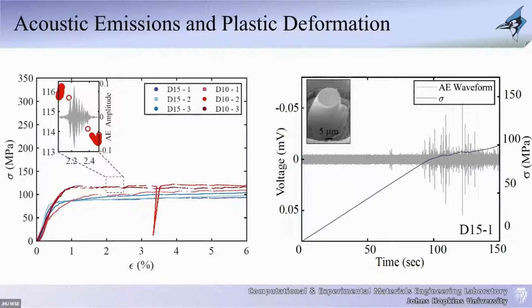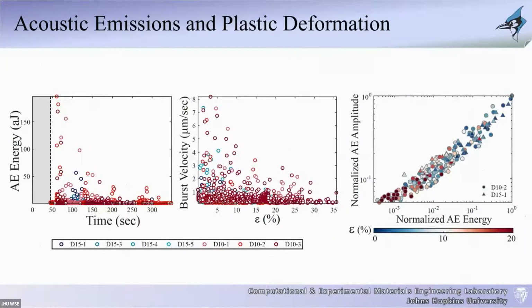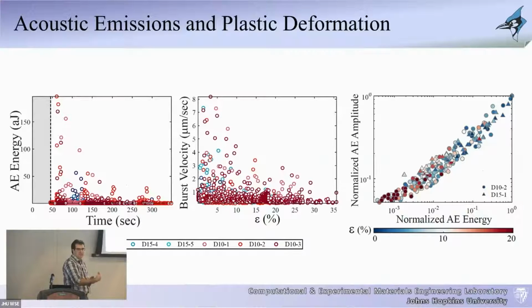What is interesting is you get microplasticity events that happen during the elastic loading, and you can actually measure those behaviors. So this basically starts giving us a significant amount of understanding of events that are happening internally in the material. Because notice now, it's not just visualizing what's happening on the surface, but I'm actually able to hear what is happening internally. So this is basically a curve that shows you some statistics associated with the measured acoustic emission energies